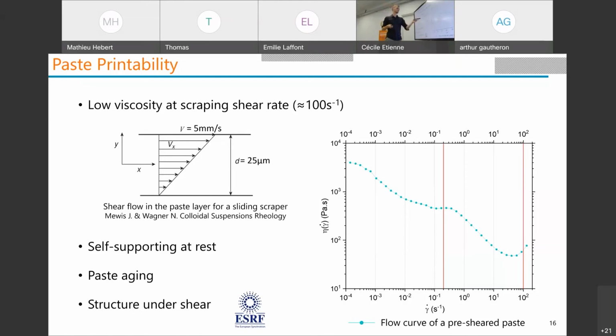I want it to be regular, so I need this type of behavior that you have with the paste in the commerce. At the right, you see a flow curve where you have a big viscosity at low shear rate and low at high shear rate. But the problem is that you see it's not regular. We have small shear thickening bumps, and this is linked to the evolution of the structure of the paste when you shear it. So we will make some experiments at the ESRF, making rheology experiments while we make SAXS, so small angle X-ray scattering, to understand the size and the type of flocs, so of particles, aggregates that could be involved in these phenomena and to avoid them.